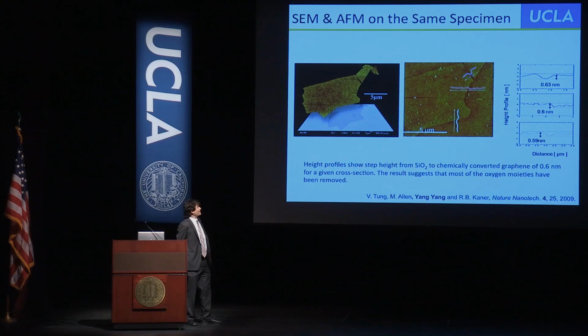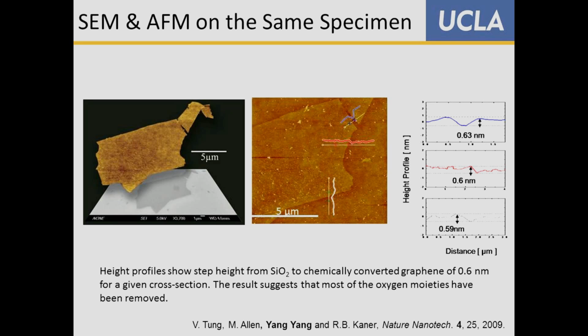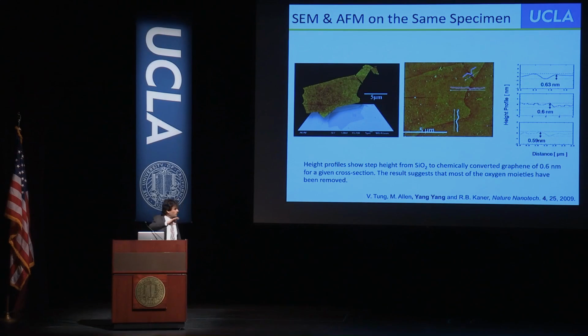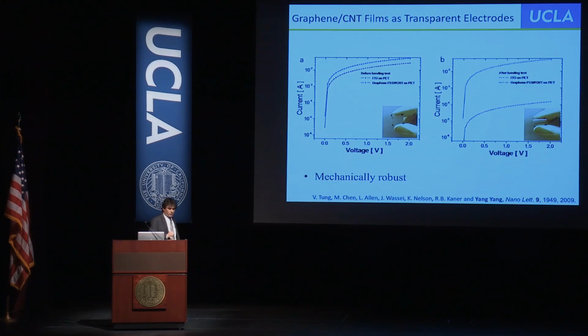So we ran an atomic force microscope probe across white, red, and blue. And what you'll see is the step height is about 0.6 nanometers. And by doing this, we could demonstrate that this really was a single layer of carbon. Okay, well, what can you do with a single layer of carbon?